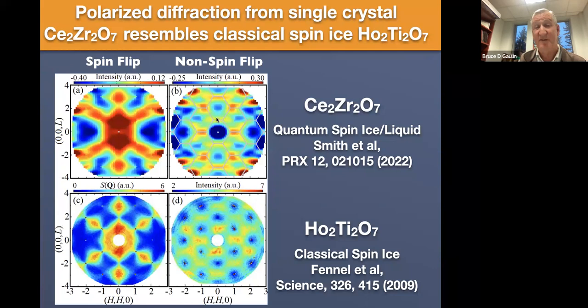We see diffuse scattering that's extended along these zone boundaries. For holmium titanate, this zone boundary scattering is not anticipated in a near-neighbor classical spin ice model, and so it has been ascribed to interactions beyond near-neighbor. And for holmium, because you've got such big moments, you actually expect to have substantial dipolar interactions.